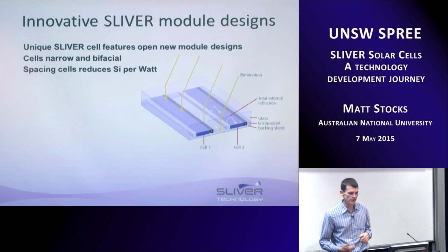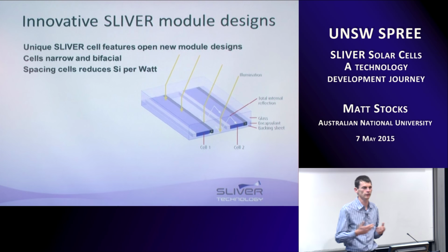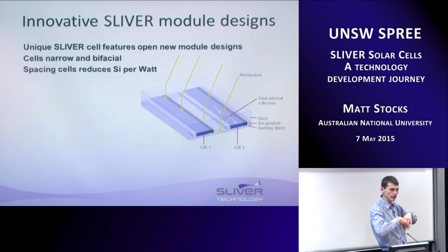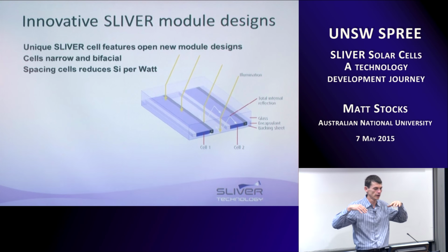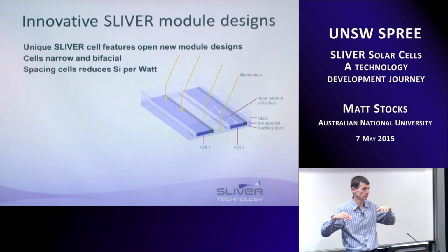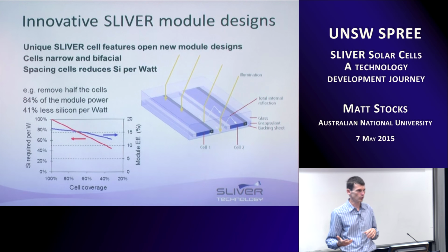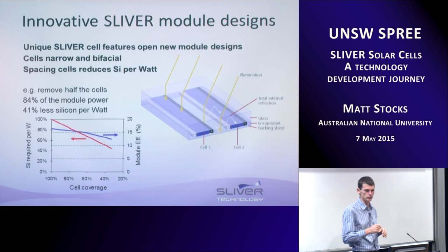But we could also save our silicon even further by spreading the cells out. So what we did particularly early on in the process was to actually take the cells and separate them and put a white rear reflector behind the cells. And that way the light that hit the rear reflector was reflected back onto the back side of the cell, and we could then recover some of the light. You don't recover all of the light though. So it's back into a trade-off situation.